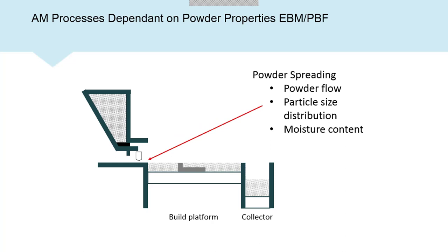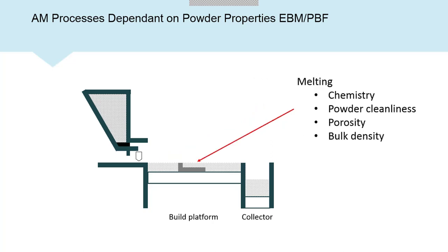I then need to spread that dosed powder. So again, what I care about now is how easily will my powder flow. Will it lock up and not spread efficiently? Will it be too free flowing and spread too much? What I want is a very nice uniform flow of powder across the build table. Again, particle size distribution, and again, moisture content, because that's the kind of thing that's going to start to affect how it flows. Then when I actually want to melt the material, now I care about the chemistry. So have I got the correct chemistry? Is my powder clean? Do I have any particulates in there that are foreign to the bulk? They're going to cause me inclusion issues. Porosity, so how densely packed is that powder bed, and bulk density.